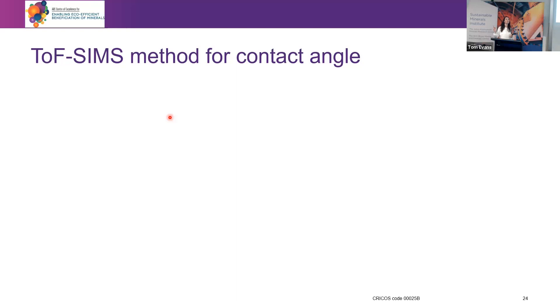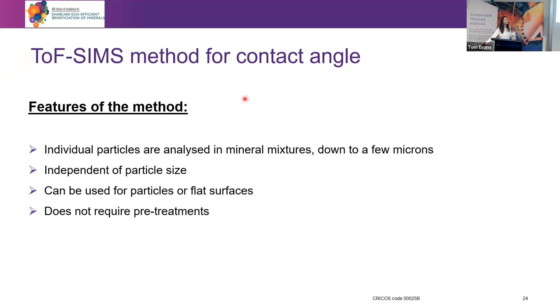This is important especially as we develop our understanding of coarse particle flotation. To summarize, this method has significant advantages: it enables us to analyze individual particles in mineral mixtures, it is independent of particle size — which is very handy because conventional Washburn methods to determine contact angle are limited to a certain size — and it can be used for particles or flat surfaces and does not require any pre-treatment.